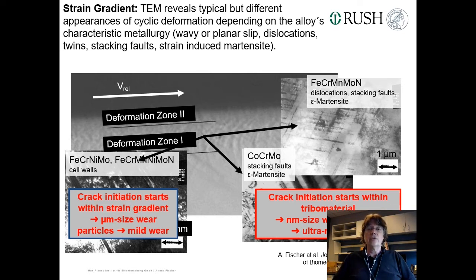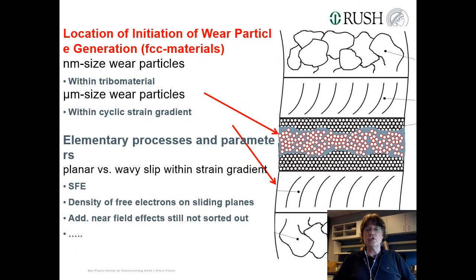So the difference between good and bad was not the hardness. It was more or less the metallurgy of the materials that are responsible for either wavy or planar sliding. So in order to optimize these systems, you need materials that would, under fatigue loading, even at high cyclic stresses, within the strain gradient, only remain on the discrete sliding planes, so that the entire crack initiation and propagation in order to generate a wear particle takes place here or here. And then the wear particles remain nanocrystalline.